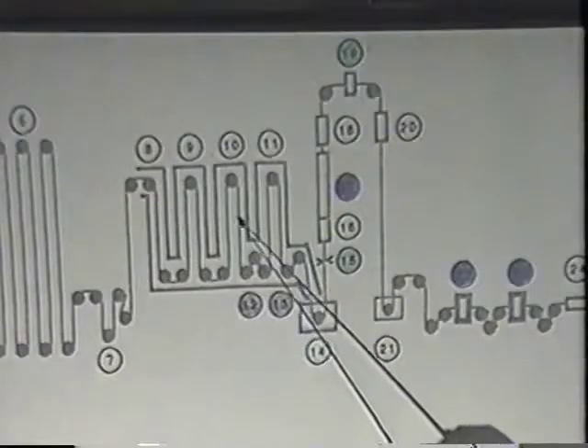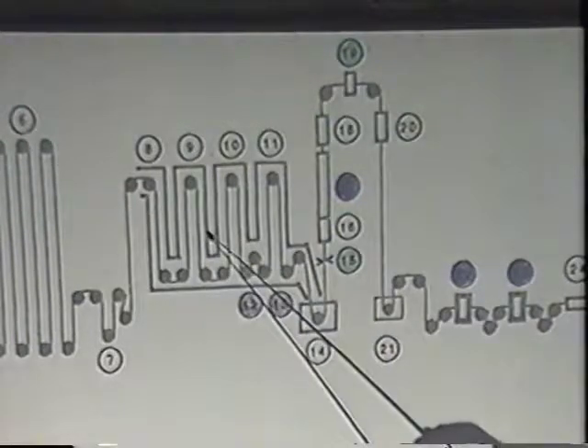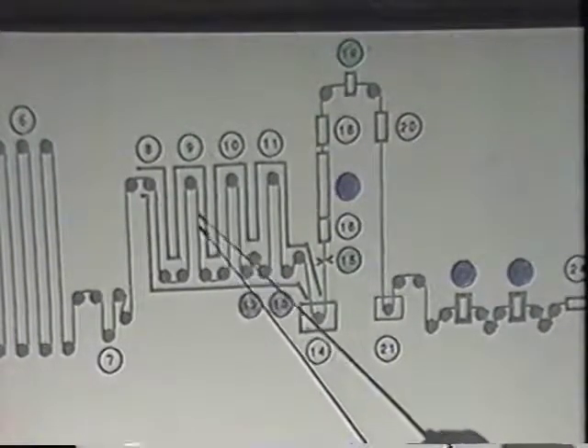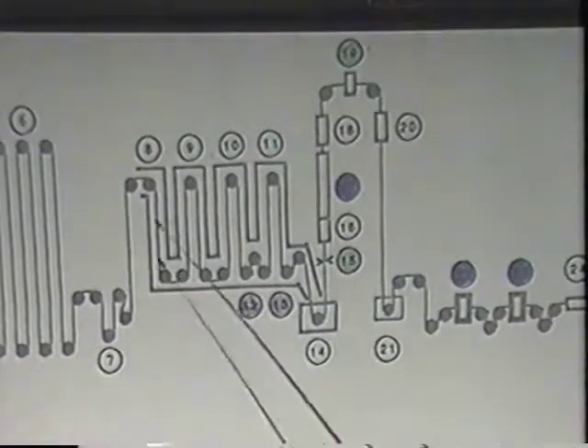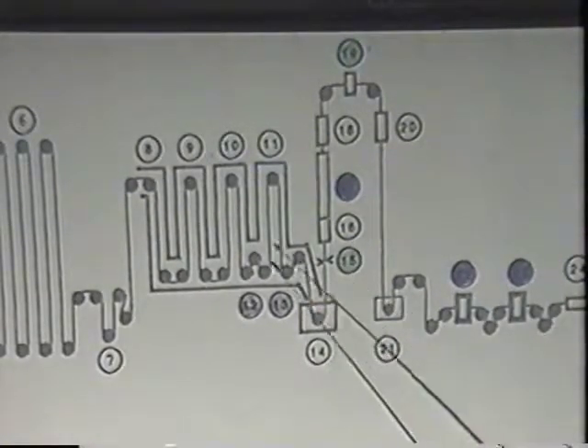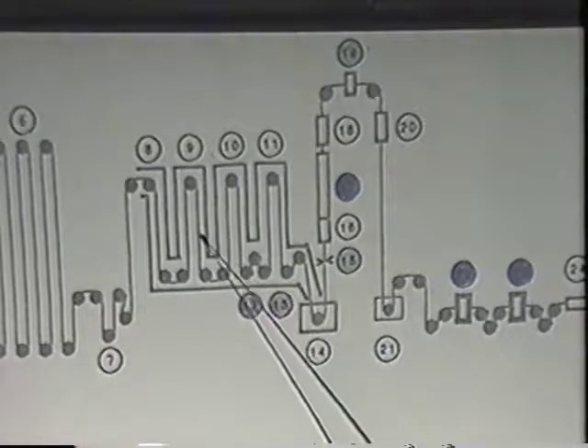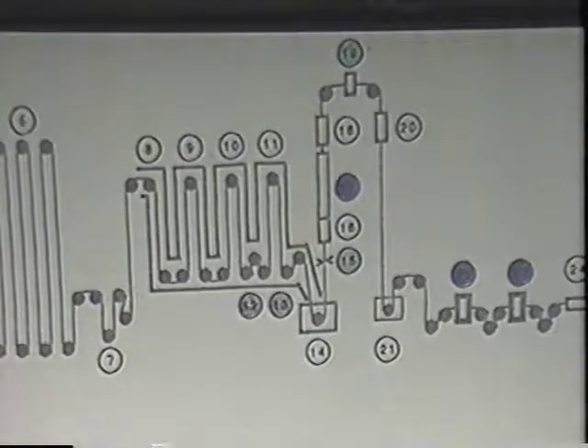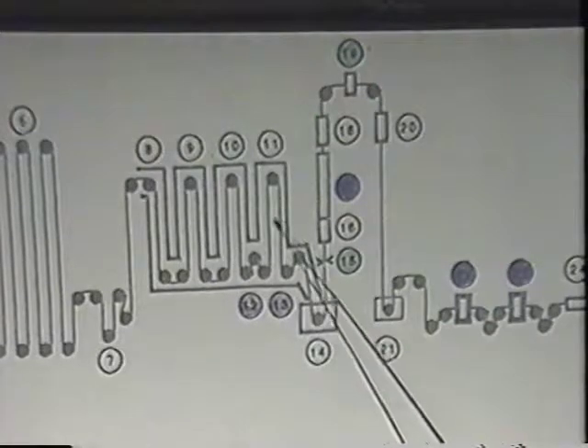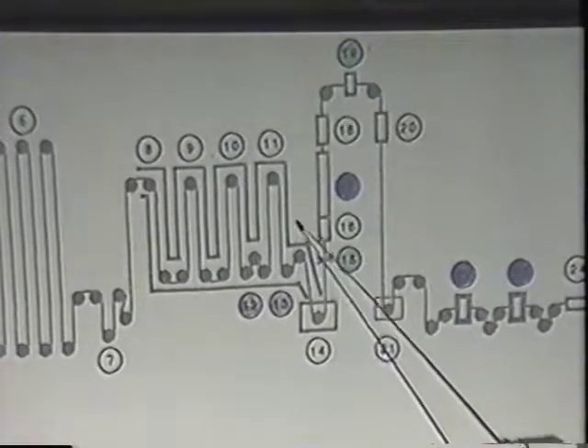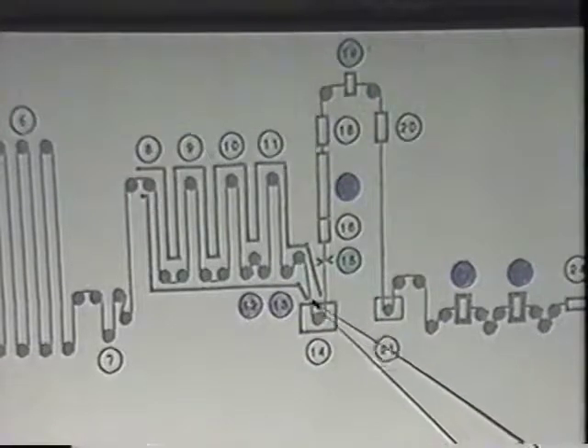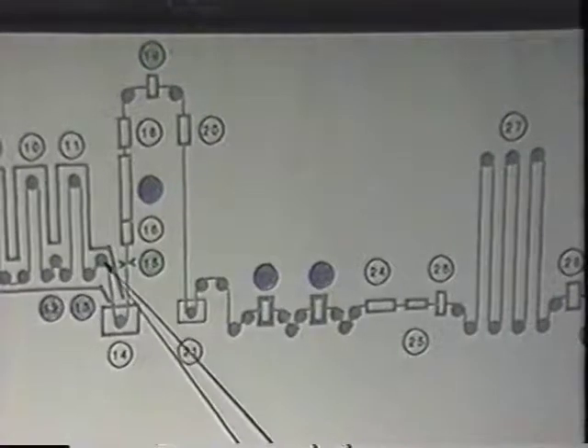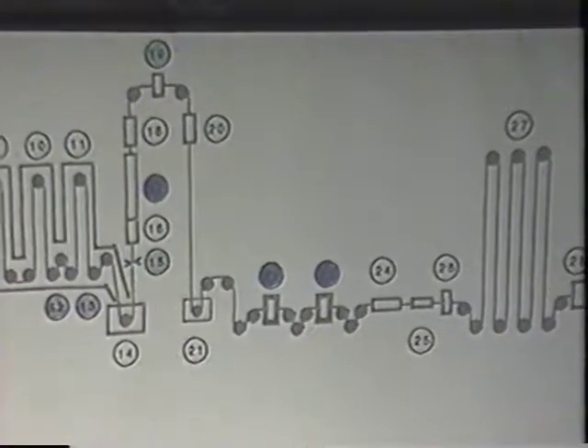Then it goes into a soak section, which basically holds it at that same temperature for just a little bit of time. It's only 30 seconds. The whole time in the furnace here is probably only about a minute and a half. So when I say soak, it's not holding it there for an hour. It's only holding it for about 30 seconds. But that's enough to let the properties sink in at that temperature. Then we go into a cooling section, what we call the combo cool. Because if you remember, I mentioned when it gets into the zinc pot, it's got to be about 860 degrees. You don't want to put a 1500 degree strip into 860 degree zinc, or it'll start bubbling away on you. So this cools it down in a controlled fashion until it gets to the zinc pot.